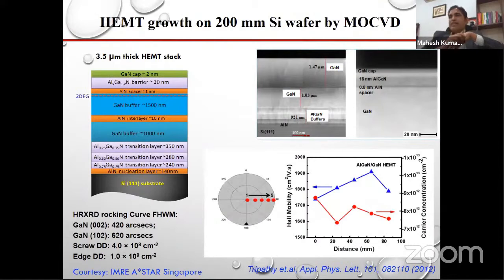So we have taken the advantage of this 2D electron gas, and first we have fabricated a high electron mobility transistor, and then we have used this high electron mobility transistor for heavy metal ion sensing. To grow this, we have to grow many layers, because gallium nitride substrates are not available, since gallium nitride decomposes before it melts. So we have to grow on a foreign substrate, and these samples are grown by MOCVD.